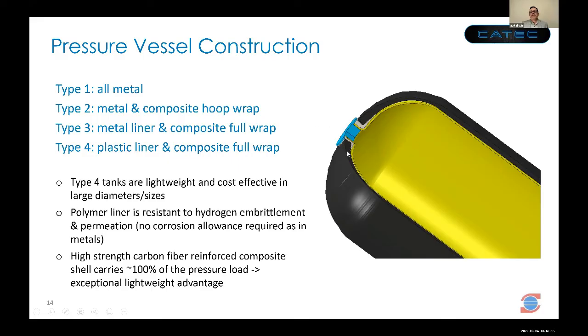And there are many requirements for these things. The polymer liner needs to be good for, let's say, -40, and good up until about 82 degrees C or so, which is the operating temperature now standardized for hydrogen. And the carbon fiber cannot be too expensive. We are not using aerospace type. The aerospace type of fiber is typically about $200 a kilogram, but we want to be using something of the order of maybe $20 a kilogram, so this is cost effective.